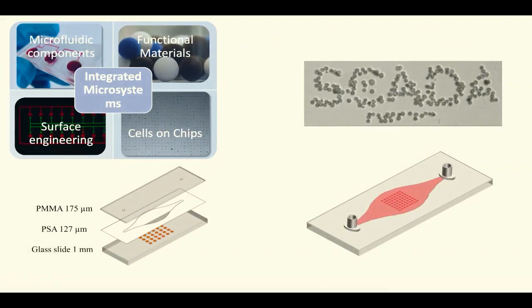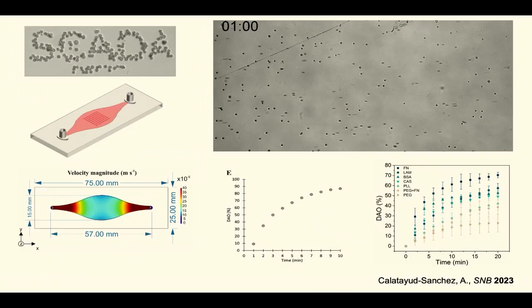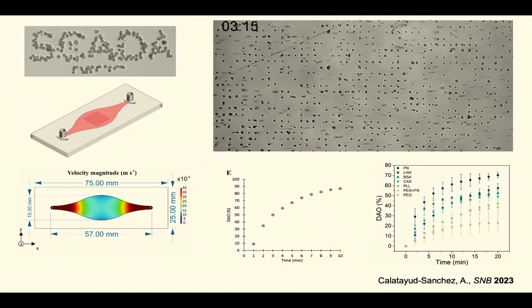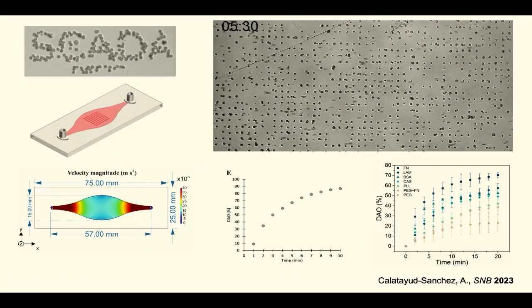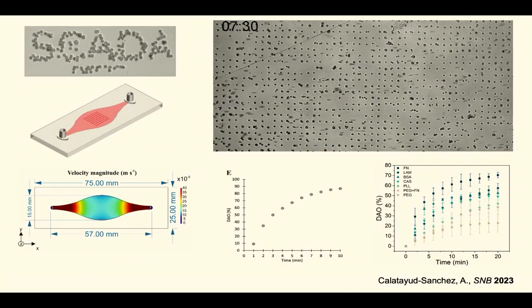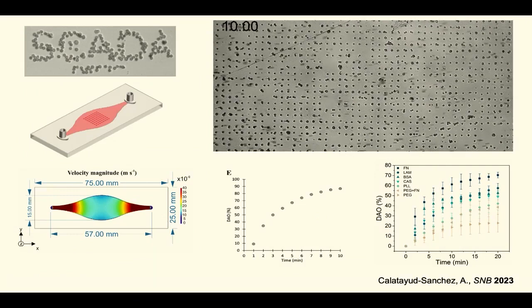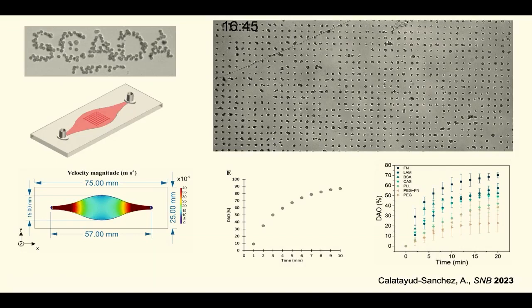So what we did was to integrate this idea into microfluidic platforms, and we do that in a very simple way. We have a substrate with the protein pattern, and then we use thin plastic layers that we can easily cut to create a fluidic gasket. And we create what we call the SCADA device, standing for single cell adhesion arrays. So what you see in this video is a cell suspension flowing over the pattern of fibronectin in this case. And the cells are mesenchymal stem cells. And you can see how the cells are adhering to the fibronectin dots, filling the array. And we can actually monitor this in real time, and we can build the adhesion curve. We can monitor that adhesion curve in 10 minutes, 20 minutes time.